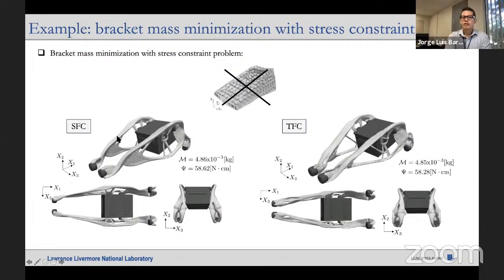And you can see these are the converged, the optimal results for both approaches, the single and the two-field coupling. Visually, you can see that there are some clear differences in the topology. However, in terms of performance, if you look at the numbers, they're pretty similar. So the findings here are that, despite we were hoping that the two-field coupling, because you have more freedom in how you evolve your design, might give better optimal solutions, at least for this type of structural problems, we couldn't see that happening.